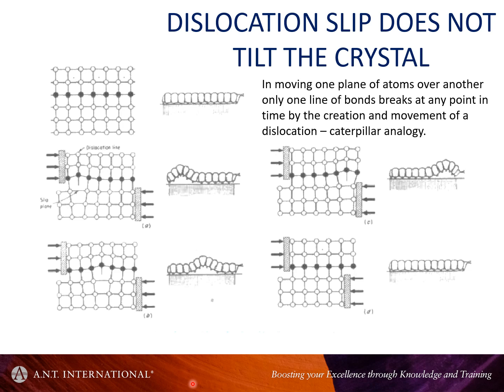the most common defect that one will deal with, and that's dislocations. So here's a very interesting note, a schematic description of what dislocation slip is all about. If we had a crystal and we wanted to shear one part of the crystal relative to another, so if we wanted to get from there to there, and these black points here are just there to denote a shear plane, or a plane where this part of the crystal will be in a different location from this part of the crystal. It doesn't mean that they're different atoms. It just denotes a plane in effect.